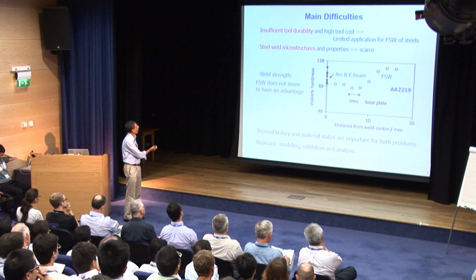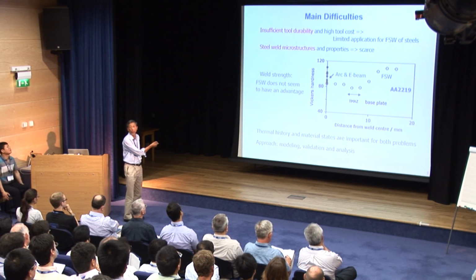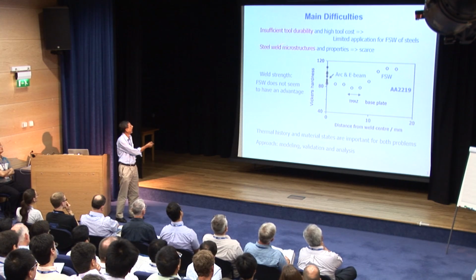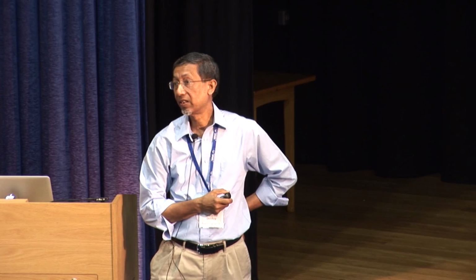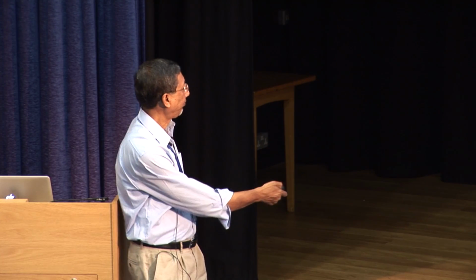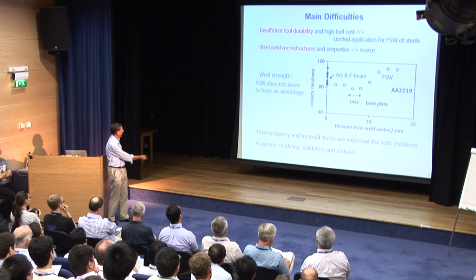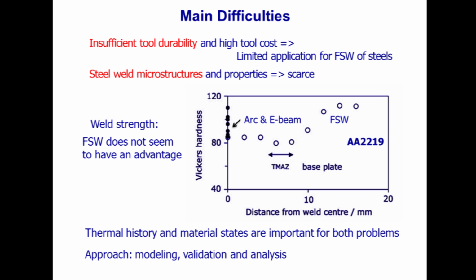So two issues: insufficient tool durability and high tool cost, the issue with the tool, and the issue with the structure and properties. They are scarce, they need to be studied a great deal before we can actually commercially use friction stir welding for steels. Thermal history, time temperature history, and the stresses are important for both problems. So the issue is, how do we get the time temperature history, and how do we get the stresses for different welding conditions for friction stir welding of steels?